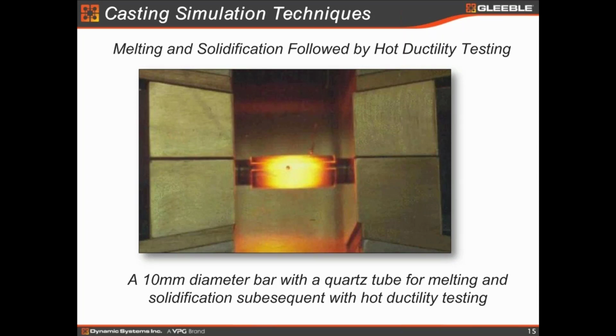So lots of things you have to study using this kind of testing in terms of stress, both the mechanical stress that you will see in the alignment roll, backing up a roll, and also the thermal stress that might be generated during the thermal gradient solidification. So controlling of the thermal gradient, control of the cooling rate, control of the solidification is very important. So this is a very popular technique that people are using.